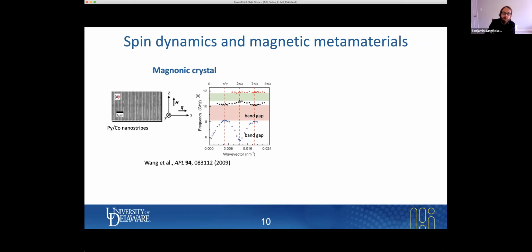So here's one example where we have a one-dimensional magnonic crystal. It's made of nickel iron, so permalloy, PY is the abbreviation for this nickel iron alloy, and cobalt nanostrips. So you can see them here. Here's the scale bar, it's 1 micron. And then there are spin waves launched at some end. And in this paper, they report the dispersion. So you can see here frequency versus wave vector. And because of this magnonic crystal, because of the Bragg reflection in the lattice, they observe well-defined band gaps in this lattice. So the bottom line here is, this is analogous to photonic crystals in photonics. The beauty here is we can control individual elements, for example, by external field routines or by spin torques.